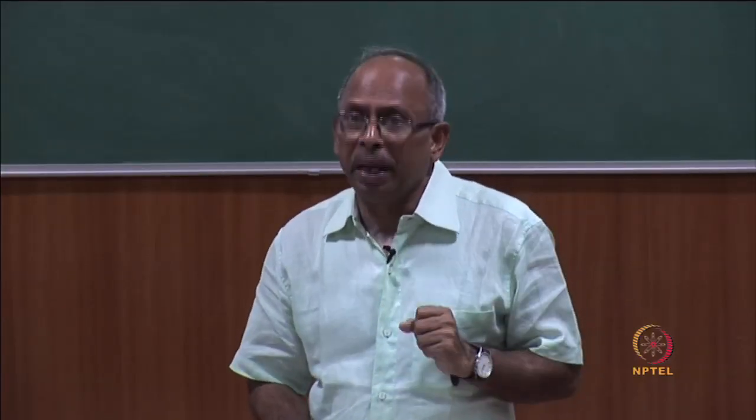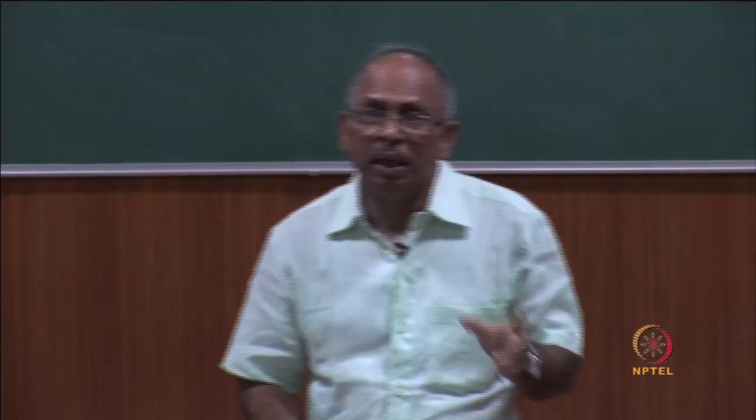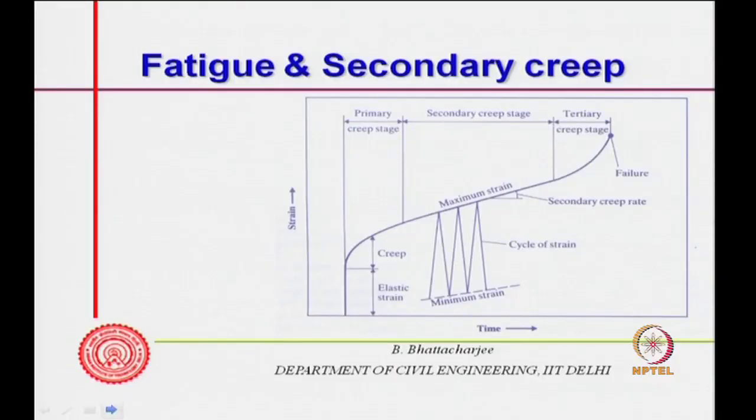Now, creep is also related to fatigue, which I mentioned in the sixth module at the end of the fourth lecture. But let us see how it is related. Many materials show this kind of behavior. If you see, this is time, this is strain, after loading. You have loaded, this is the elastic strain, remember, then there is creep. But beyond a certain stress level, this goes on increasing. In concrete, at normal lower load levels, it tries to be asymptotic, but in many materials the slope gets reduced and it becomes a linear, constant rate increase. And as you go further,